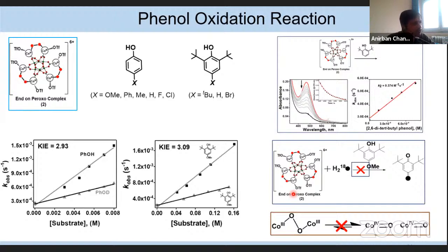So to prove again whether there is formation of any high valent metal oxo species or not, I did the reaction in presence of 18O labeled water, and I didn't see any kind of 18O incorporation product in GC. So from the lower KIE value and the 18O labeling experiment, I conclude that there is no high valent metal oxo species forming in the reaction, and it is only the dinuclear cobalt(III) peroxo species which is responsible for the phenolic O-H bond activation process.